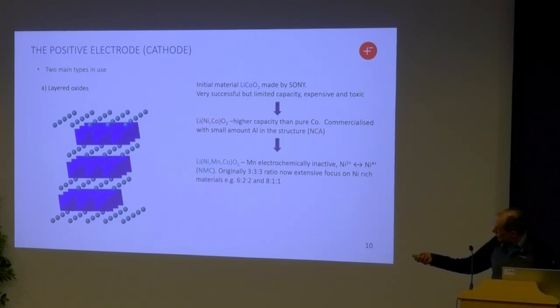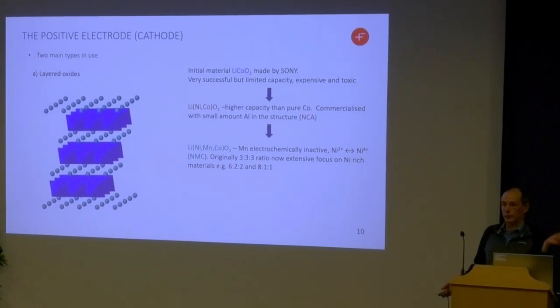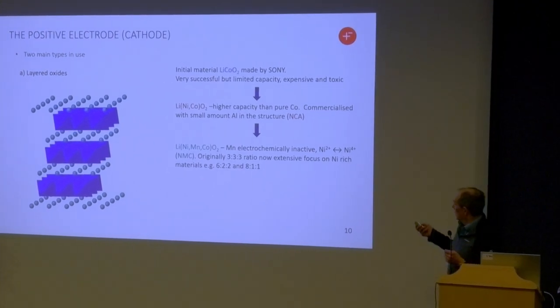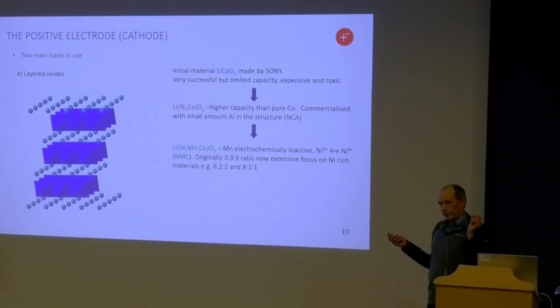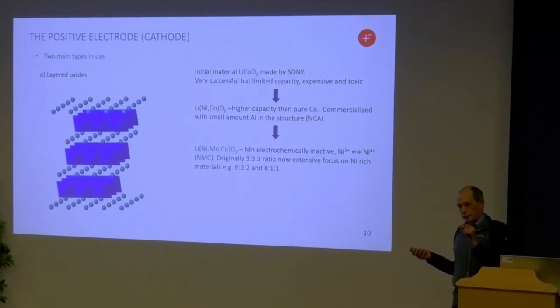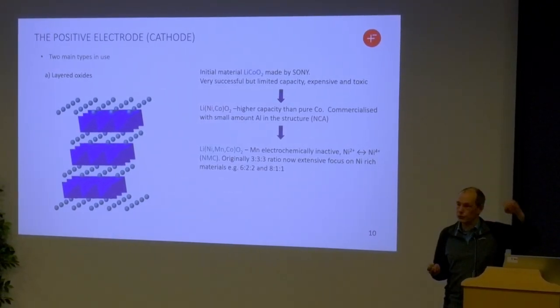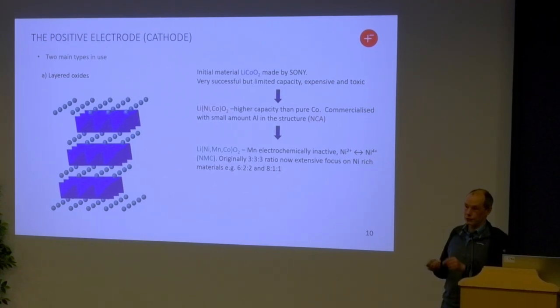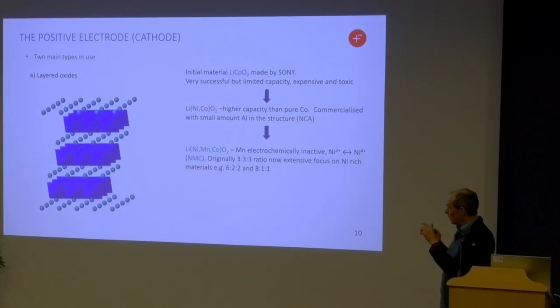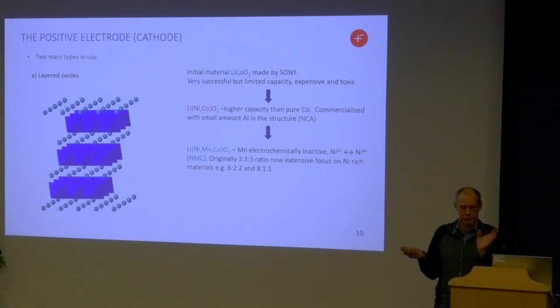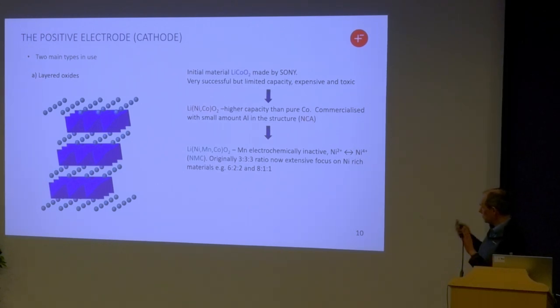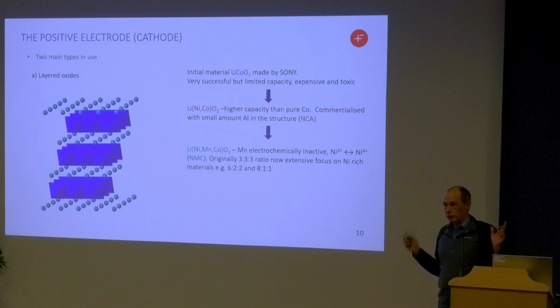So when you charge it up, you can take the lithium ions out from between the layers. It's very successful, it's very reversible, but if you take out more than a certain amount of lithium, then it ceases to be quite so reversible. So typically that's about half the lithium in the structure. So that limits the capacity. Cobalt's quite expensive, cobalt's quite toxic. But Apple still use it in iPhones.